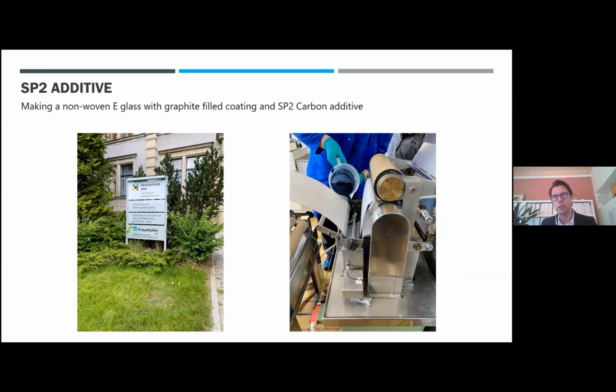I just want to spend 2 slides only, but also very quick. We're not only looking into how we can bring a paste into the resin system, we're also looking into whether we could do anything on the reinforcement side. So like Tim said, of today's usage, about 20 to 24% of the carbon fiber actually in use is used due to the conductivity, not necessarily because of the mechanical weight performance. Those are areas where we believe, and we have done some work, we are able to use, as an example, an e-glass surface veil replacing a carbon surface veil, a different cost position. We've developed a specific carbon additive, and you can see on that picture, this is where there's an impregnation phase into an industrial line of impregnating, in this case, a 20, 50, 90 gram surface veil.